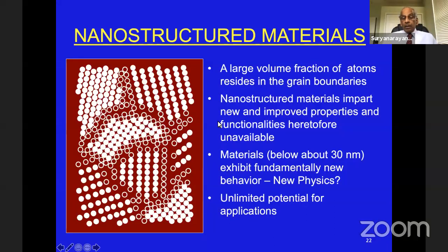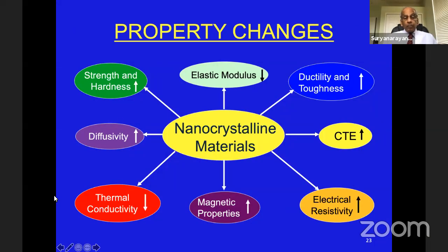You can have new and improved properties and functionalities. If the grain size is less than 30 nanometers, materials behave even completely differently, and therefore people feel that there is unlimited potential for applications of these nanomaterials. You can have all these property changes as a function of the grain size. If you take nanocrystalline materials, you can increase the ductility and toughness, but at the same time, you can also increase strength and hardness. Typically, in a coarse-grained material, if strength is high, ductility is low, but in nanocrystalline materials, you can achieve both of them.